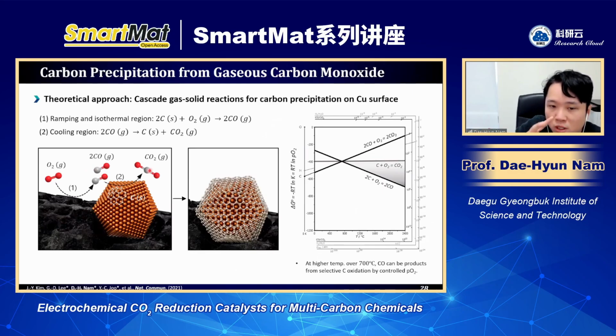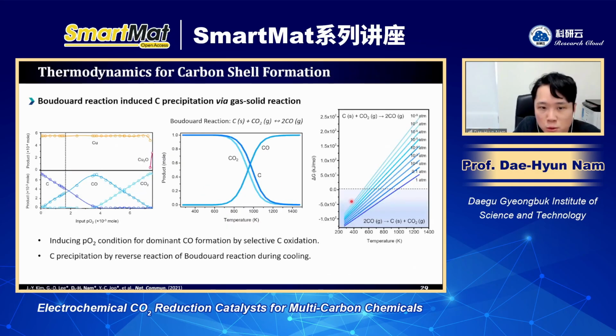And then by controlling the temperature and the pressure, we can induce the reaction direction to the fabrication of solid carbon on the surface of copper. So we designed this procedure based on these thermodynamic principles. We also did some free energy calculation to see what would be the optimal processing window to produce this kind of carbon precipitation. In that way, we could induce a reverse Boudouard reaction to produce a carbon shell on the surface of copper.